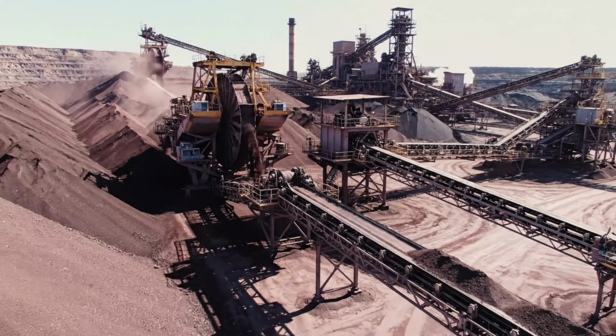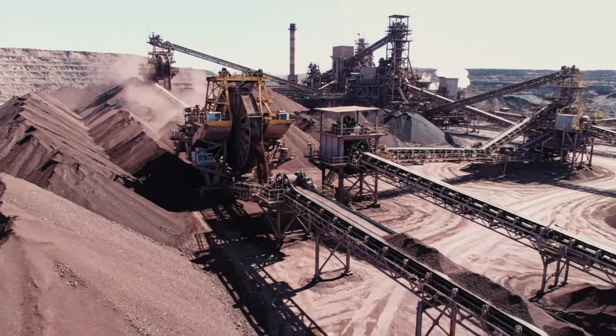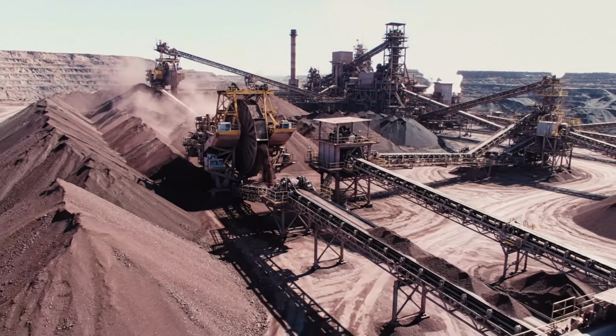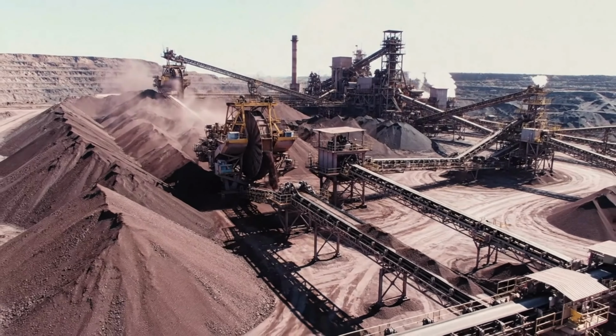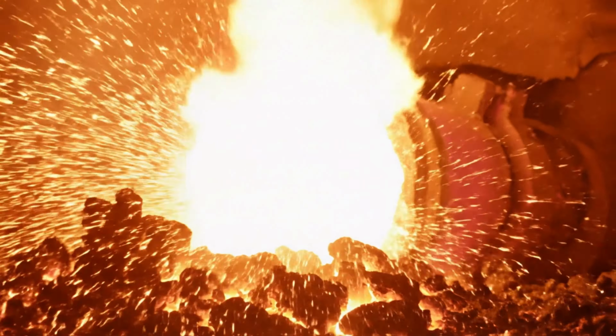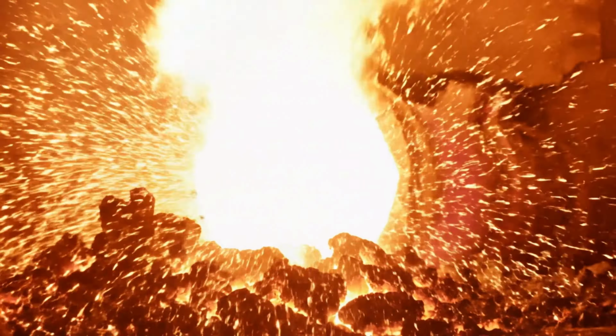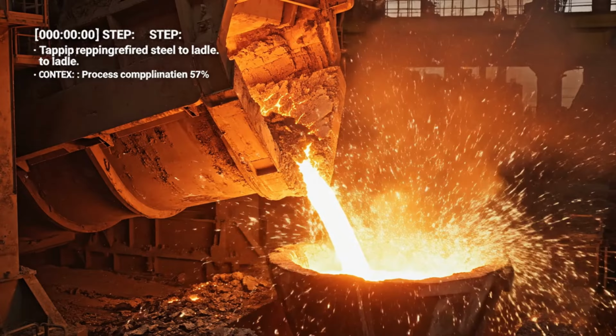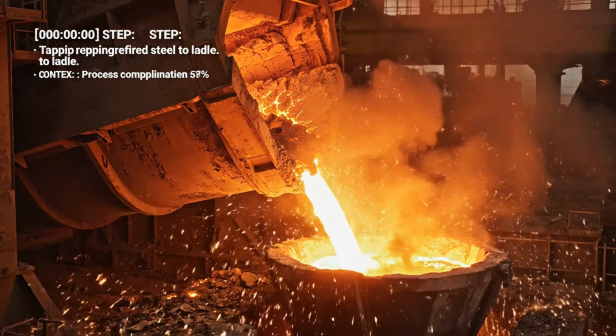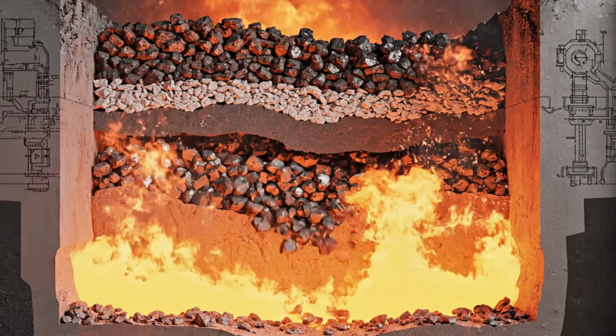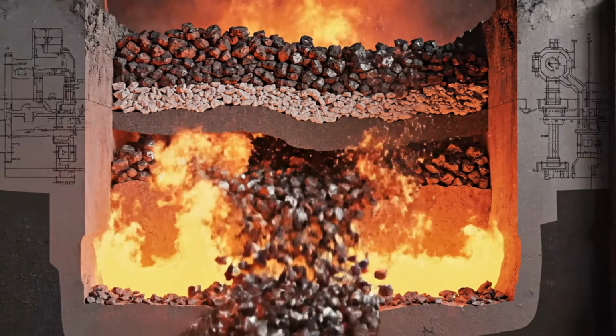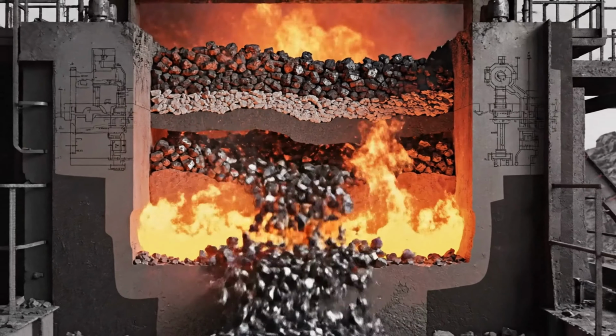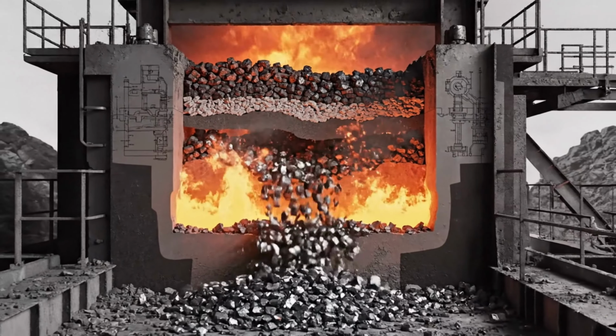Fine ore is reclaimed from the yard and sent to become sinter for the blast furnace. The hot blast ignites coke and drives the reactions that turn ore into iron. When the chemistry is right, the converter pours liquid steel into a ladle. As hot gases rise, they remove oxygen from the ore and leave behind metallic iron.